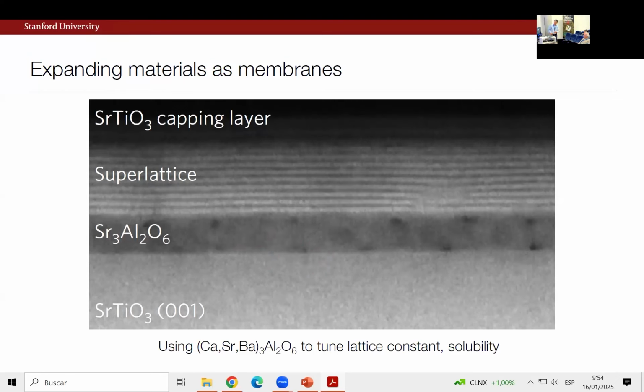Oh, okay. So now I catch your point. Forgive me, I don't remember the exact numbers, but there's a slight lattice mismatch, right? And so, for example, I think it's reasonable to presume that as you start to grow whatever on top of this buffer layer, it's going to conformally strain to that strontium aluminate (Sr3Al2O6). The usual argument is then you go above some kind of critical strain energy and something has to give. I think the point is that as far as we've looked at, probably not systematically enough, we generally find if we have a perovskite substrate, perovskite on top, the dislocation cores are living in this buffer layer.